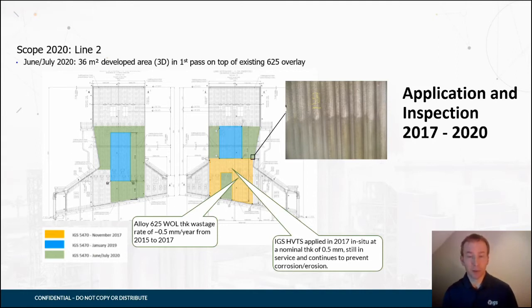The high velocity thermal spray system is applied at a thickness of 0.5 millimeter. So there's also the benefit to the client of this system not installing so much weight into the unit, and the flexibility to apply the system over larger areas on each outage, as the application speed is approximately 3 times faster than you can achieve with weld overlay.